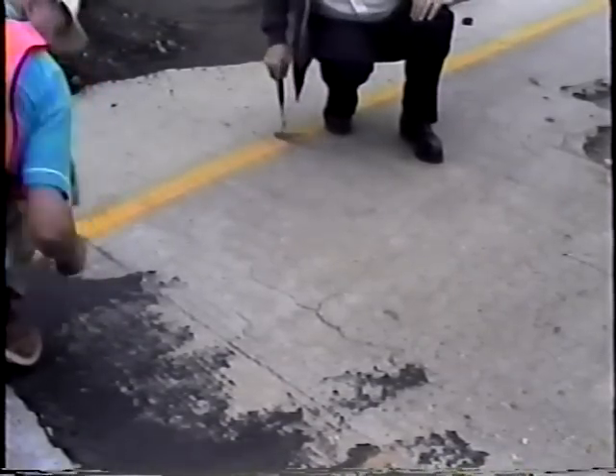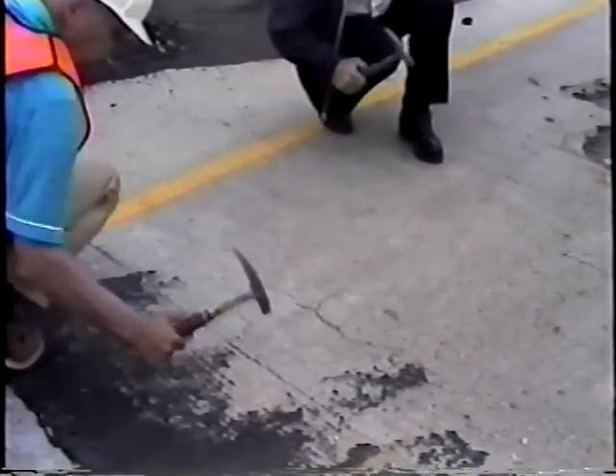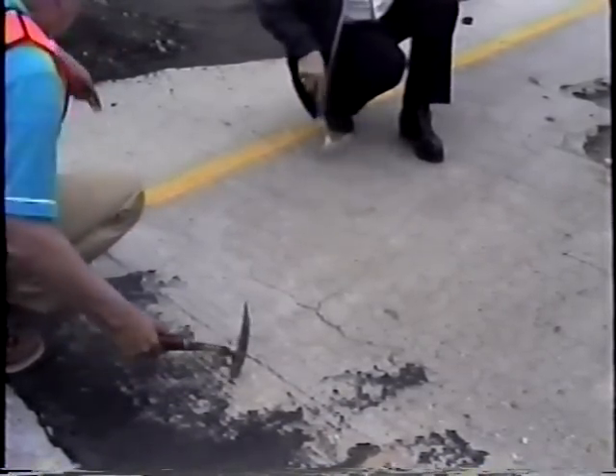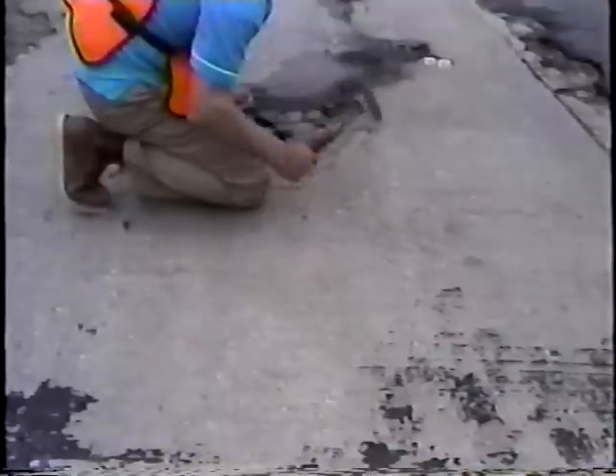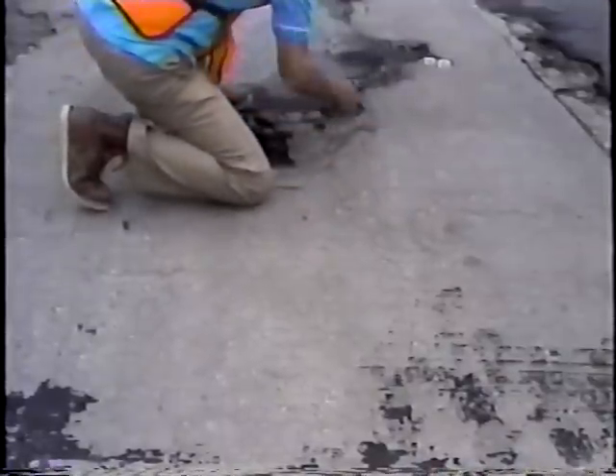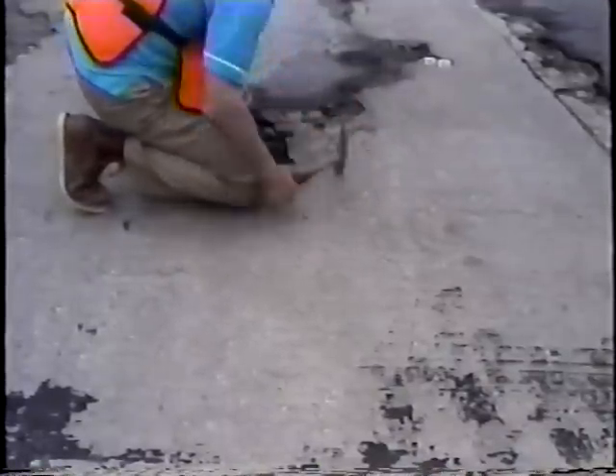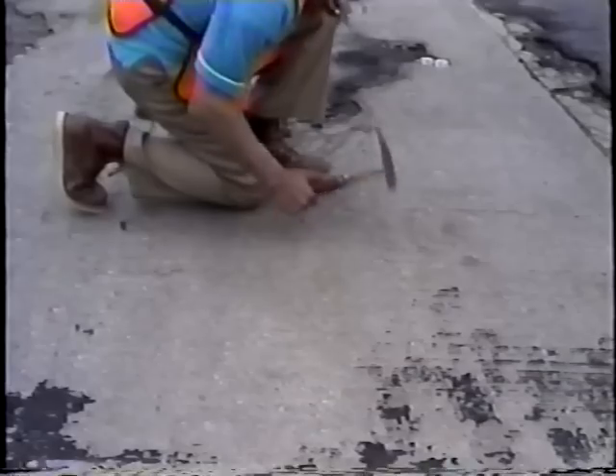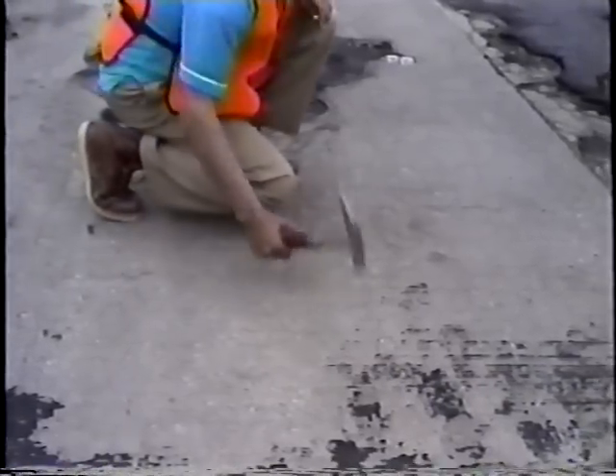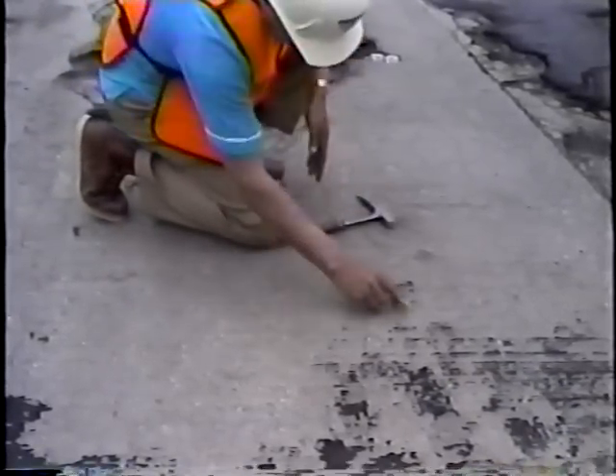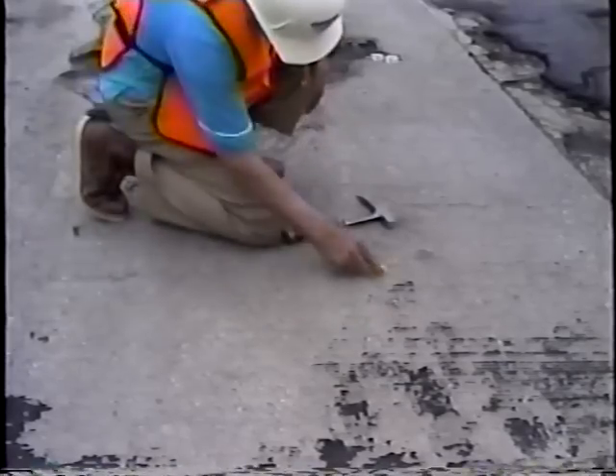A clear, sharp metallic sound indicates good concrete. A hollow, dull sound indicates deteriorated concrete, areas of the pavement that need to be repaired. Once the exact repair boundaries are established, they should be clearly marked.